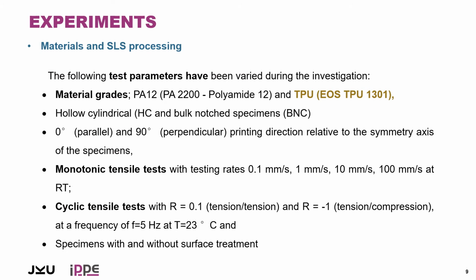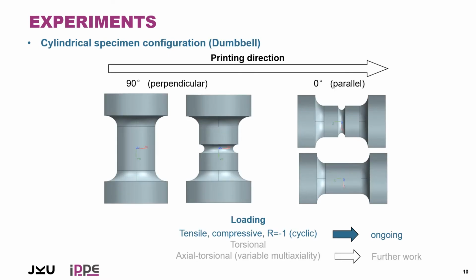Then the experiments: we use different parameters. First, the material grades, as I mentioned, polyamide 12 and thermoplastic polyurethane. We use different cylindrical specimen geometries. Also, we applied different printing orientation or printing direction. It means we used specimens perpendicular and parallel to the printing direction.